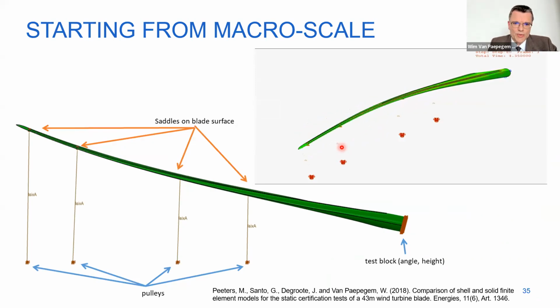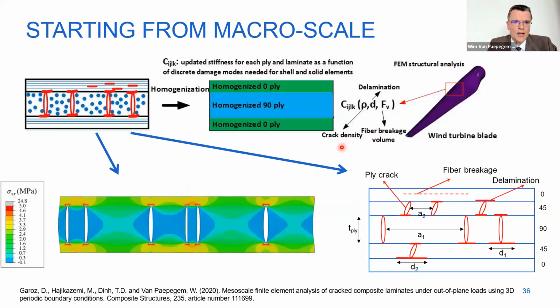But now back to our damage story. Here we have quite coarse meshing, let's say, compared to the damage mechanisms at micro scale and how to deal with them. So schematically, we have our ply cracks. I showed you the delaminations from the crack tips. We can have fiber failure and how to represent that. We could opt for an approach where you homogenize the material in between, like we did in the micro scale, but still keep the individual ply cracks modeled and even delaminations. I hope you understand with me that this is still computationally impossible. So we make these models on a smaller scale to validate our models, but we don't proceed in this direction.